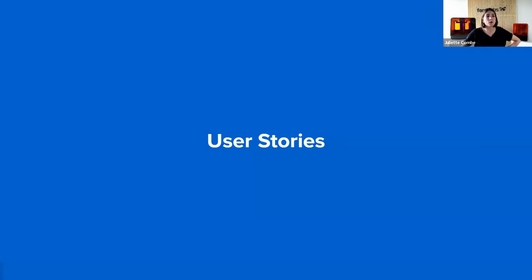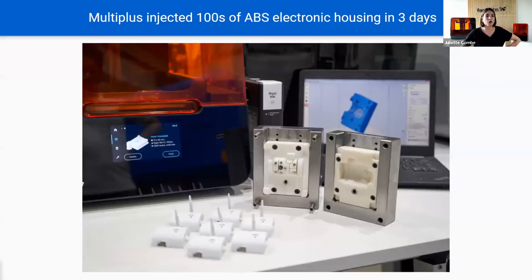So now I want to show you some concrete parts and some concrete examples of users that have been using 3D printed molds for their projects and for their business. The video that we showed before from our partner Multiplus was made with a Rigid 10K mold. It is placed inside a metal frame, which is something we recommend to absorb as much as possible the pressure from the process. They injected ABS, but also polypropylene and some ABS and PC material. They were manufacturing electronic housings, and they were doing that in just a few days.